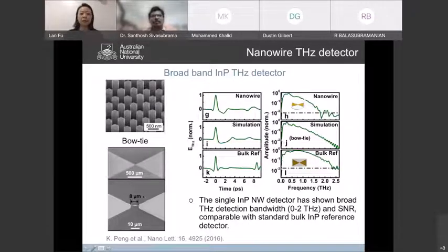First, we demonstrate a broadband indium phosphide terahertz detector based on those nanowires. Basically, we transfer the nanowires onto a quartz substrate, and through photolithography make contacts on either side of them, so that we can make a bow tie type of terahertz antenna, as you can see here. Then we put it into the terahertz spectroscopy system at our collaborator at Oxford University, and demonstrate that the nanowire can serve as a really good terahertz detector.